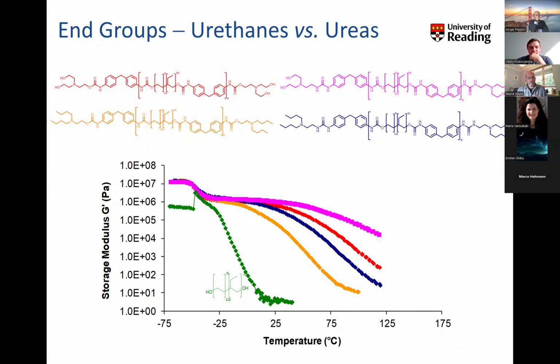So you have a stiffer material over a longer temperature range. And that is simply due to the urea's hydrogen bonding. Ureas are known to stack via bifurcated hydrogen bonds, and that's what we think is happening here. So very, very small molecular changes in these supramolecular polymers have very drastic effects on the mechanical properties.